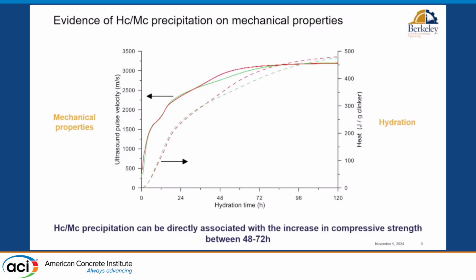And I think that the ultimate confirmation came by comparing calorimetry with in situ ultrasound pulse velocity, which is related to the elastic modulus. And as you know, elastic modulus evolution is directly correlated with development of compressive strength. We actually have an equation in 318 to relate the two things. And what we observe is that since the precipitation of carboaluminates in calorimetry, we know that it's related with the metakaolin content, well, we see the same kind of decoupling in the mechanical signal. And now we can associate a kinetic feature, a heat release, that we know corresponds to a chemical reaction with mechanical consequences of that precipitation.